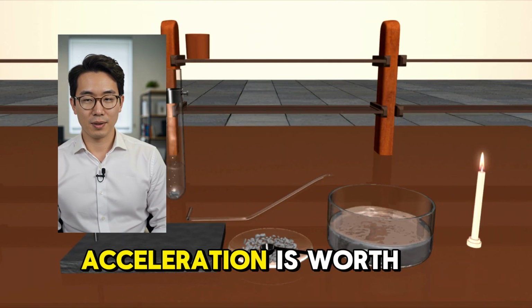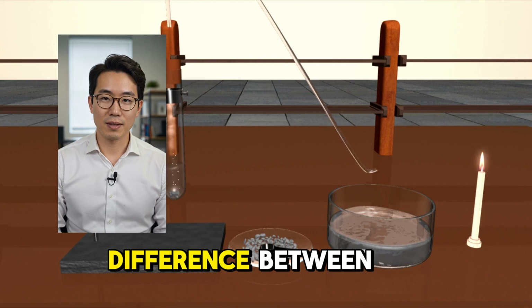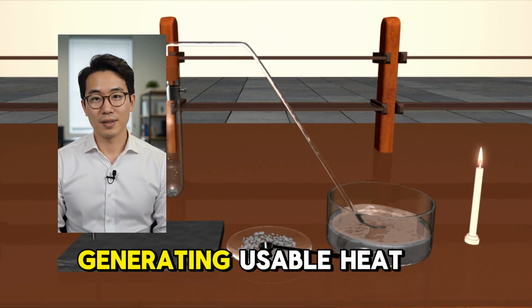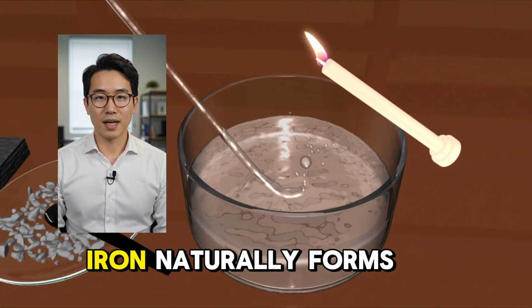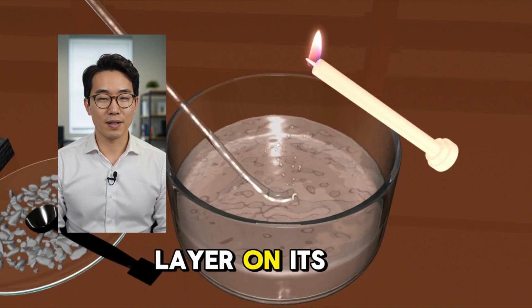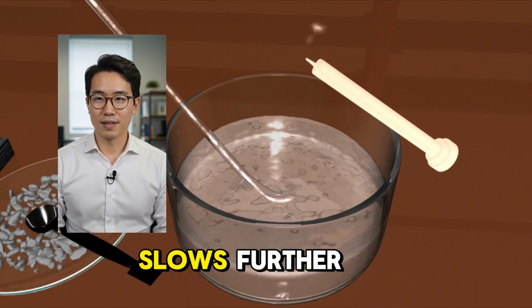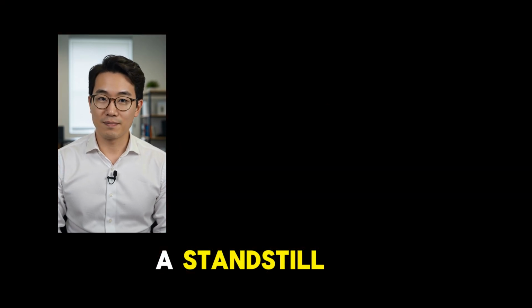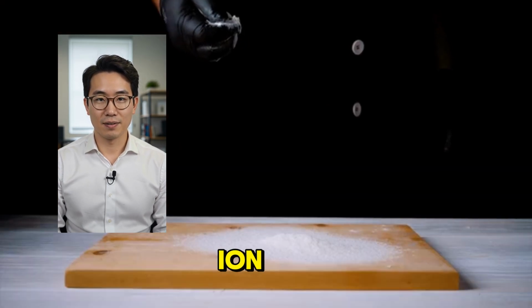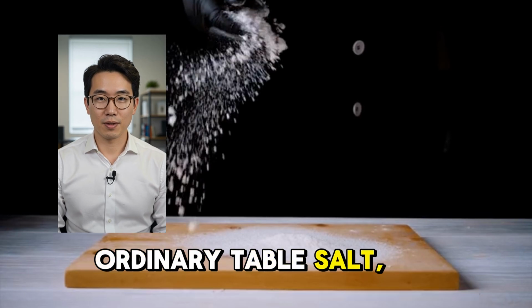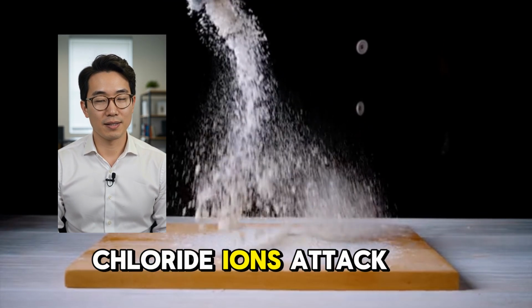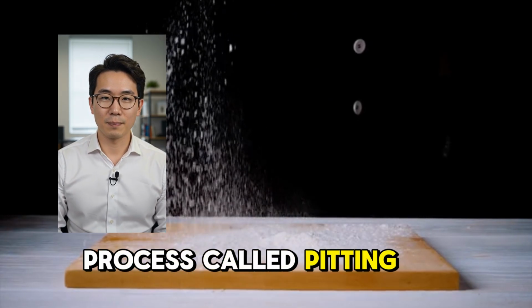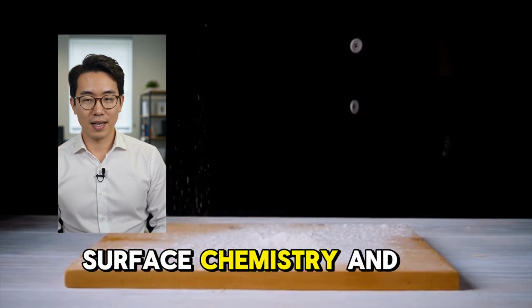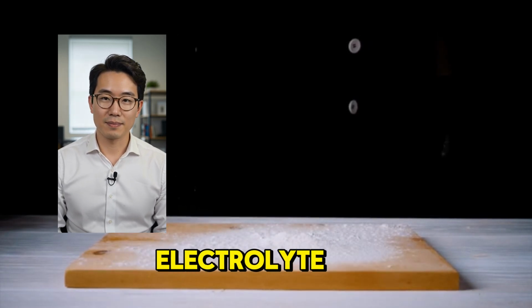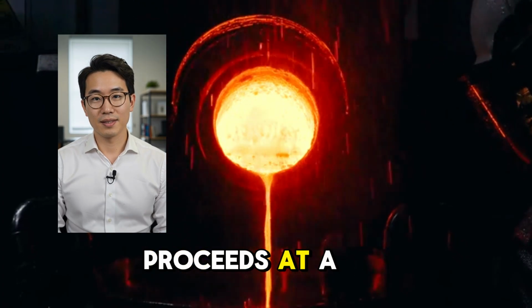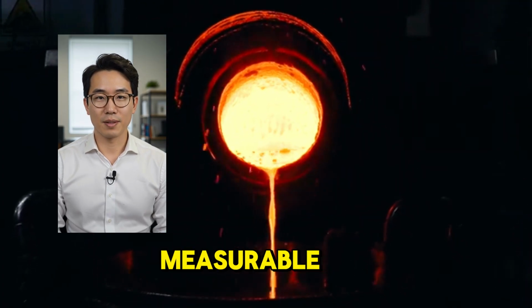The mechanism behind the acceleration is worth understanding because it is the difference between iron slowly rusting over weeks and generating usable heat in under 10 minutes. Iron naturally forms a thin, passive oxide layer on its exposed surface, a microscopic shield that slows further oxidation almost to a standstill. What dissolves that shield is the chloride ion, released when sodium chloride, ordinary table salt, dissolves in water. Chloride ions attack the passive oxide layer through a process called pitting corrosion, penetrating the surface chemistry and exposing raw reactive iron to the electrolyte. Once that barrier is removed, oxidation proceeds at a rate that is not gradual. It is rapid, measurable, and heat-releasing.